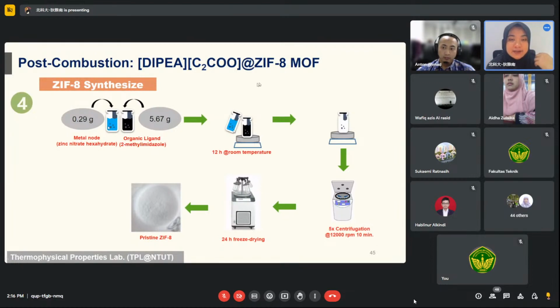So we synthesize first. We don't use any heat to synthesize. We just use room temperature, so we can save energy, for around 12 hours. Actually, we have tried 4 hours or 8 hours, but under the optimum synthesis condition the yield is not that much. That's why we leave it for 12 hours; it's more ZIF8 that we can obtain. Once it's totally mixed, we do the centrifuge at 12,000 RPM, and we wash with water 5 times.